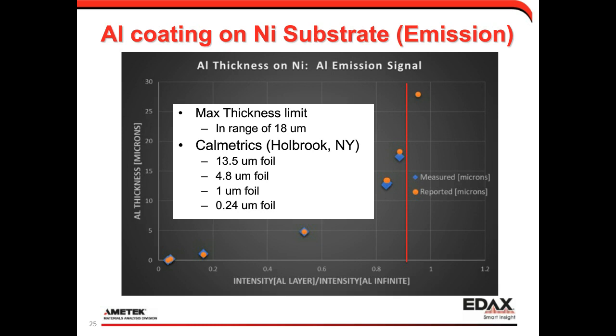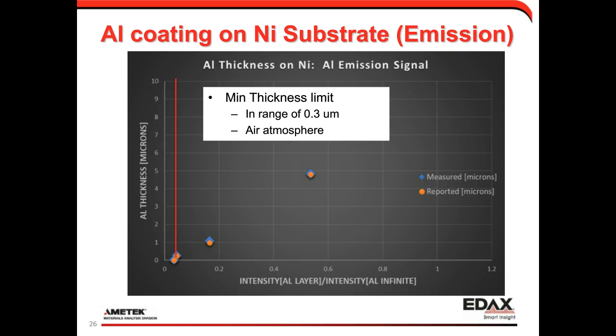In the 13 to 18 micron range, when we're doing a single point calibration at around 5 microns, our accuracy is in the range of about 10%. We could make that better by adding a calibration point out in the thicker end of the region. This is the kind of thing I would expect to see in this region. And as we blow up the thickness axis on the Y, so now we're at a total range of 10 microns, you can see the values that we're getting for the 1 micron value. The accuracy there is around 5%. The 1/4 micron is again around 5% in this particular case.